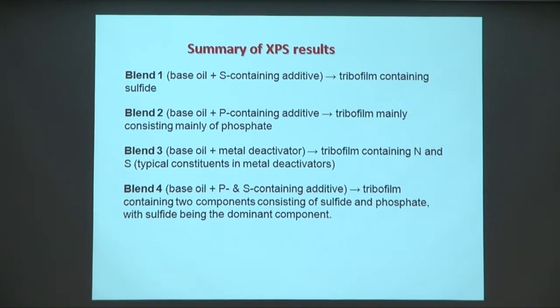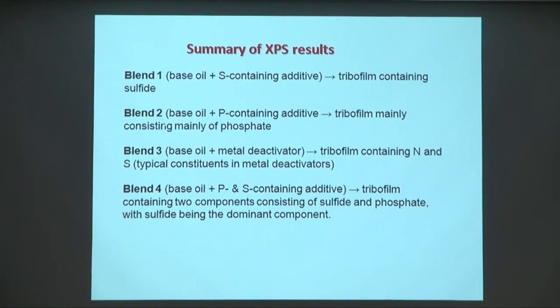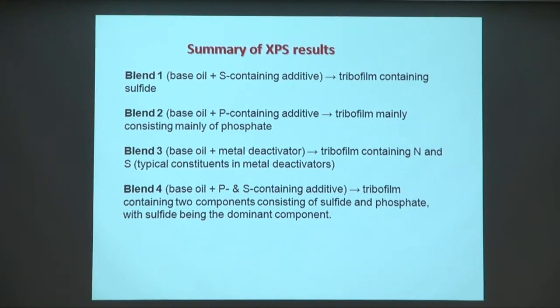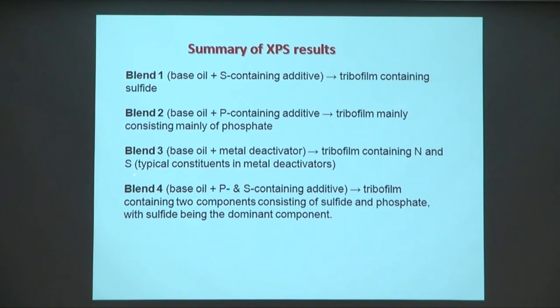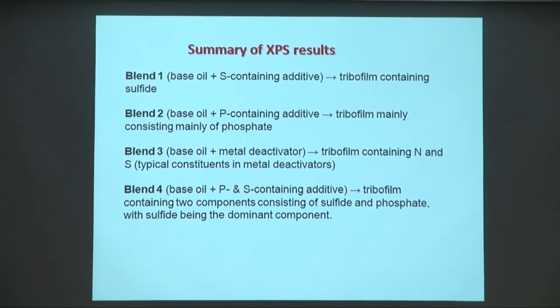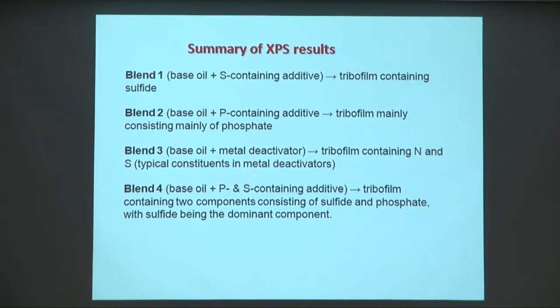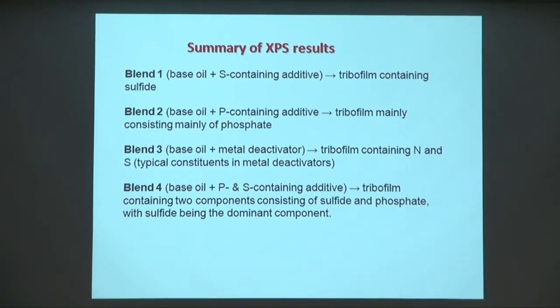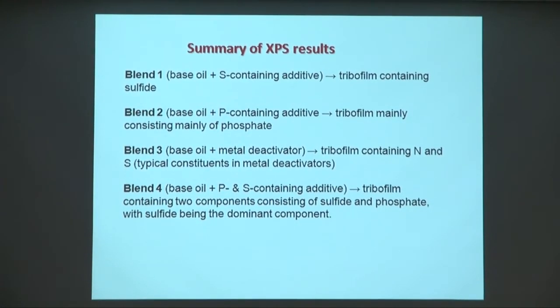The second blend that has the phosphorus additive, it formed a film that was mainly consisting of phosphates. And the blend 3 that had the metal deactivator had the tribofilm that contained nitrogen and sulfur. This is what the chemical analysis showed, which are typical constituents of the metal deactivators. This was performing better than that, and even better than that, which is the phosphorus and sulfur containing oil.